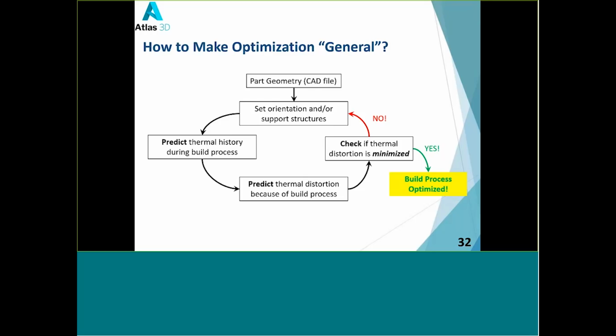This is the general optimization method. Because you need to deal with different geometries of the part, usually we will take the CAD file as the model input, and we will initialize the part with one orientation, and we will set the support structure for this orientation, and we will predict temperature history and predict thermal distortion. If the thermal distortion is minimized, we can see that, okay, the optimization is done. Otherwise, we need to change the orientation and do another iteration of optimization.